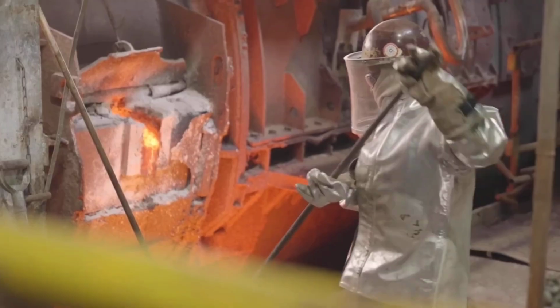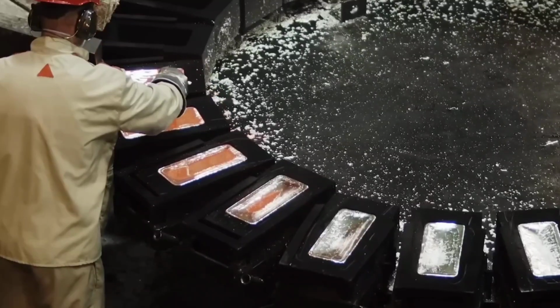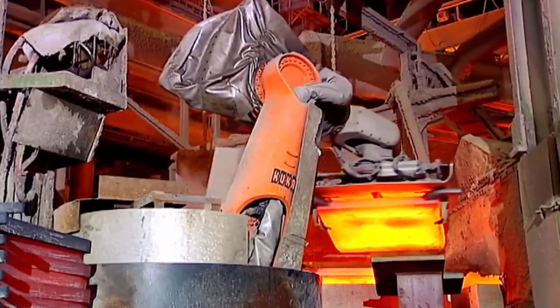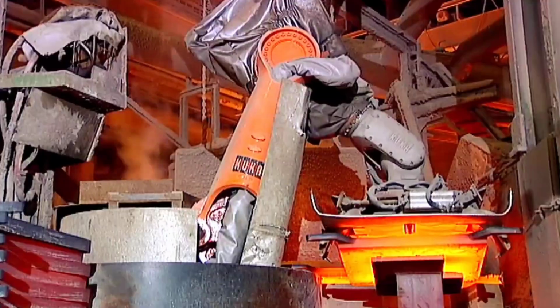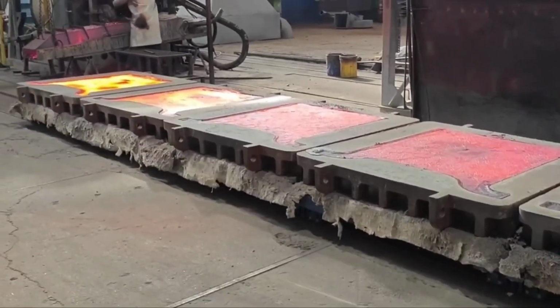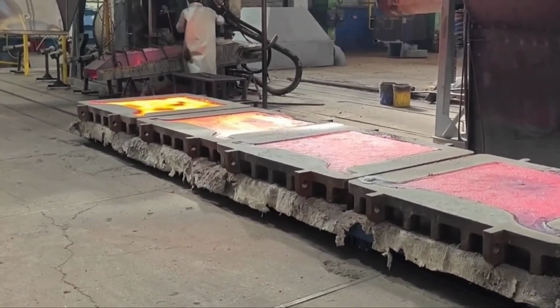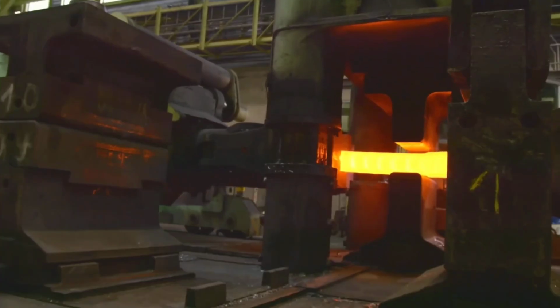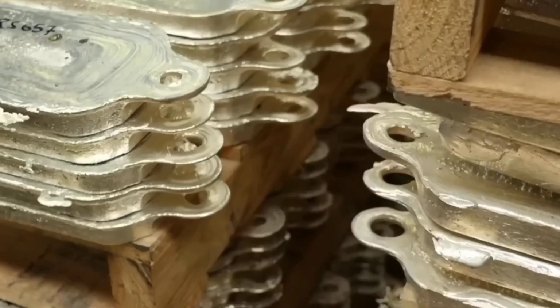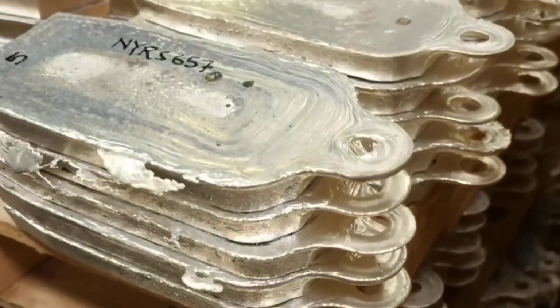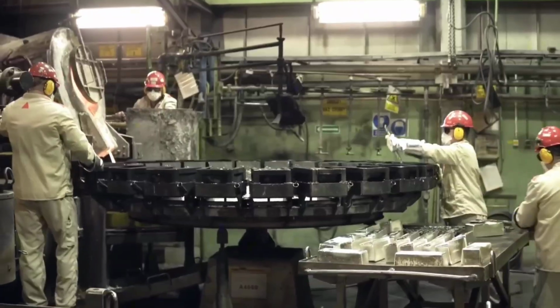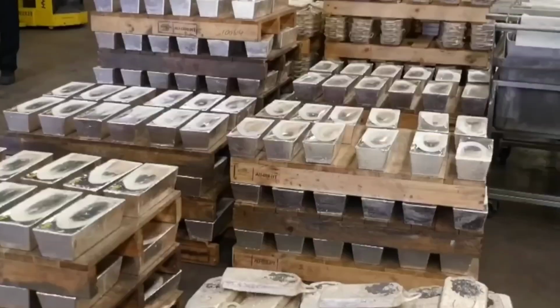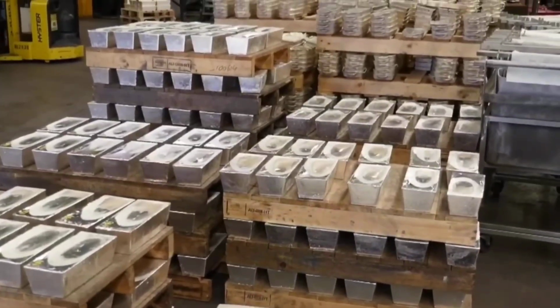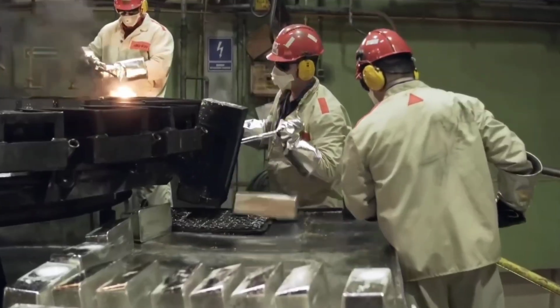The mold surfaces are coated with a layer of graphite-based release agent, allowing the silver to flow freely without sticking to the walls. Each raw silver bar typically weighs between 25 and 30 kilograms and still contains small amounts of other metals, such as copper, lead, or gold. This is the moment when silver takes on its definitive shape, no longer ore, no longer mineral slurry, but a solid metallic entity.